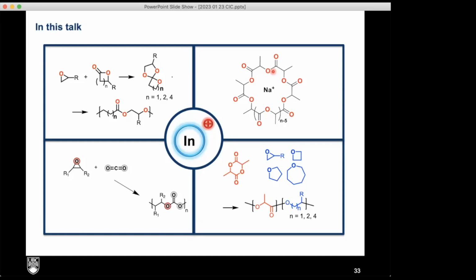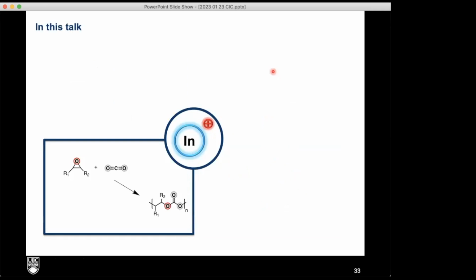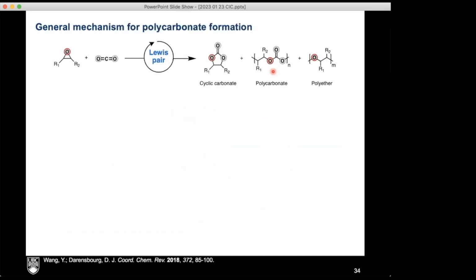And so the final part of this story is looking at the copolymerization of two more stories. The next one is the copolymerization of epoxide and CO2 to give polycarbonates. So this one is actually not a cationic indium, but I'll show you why that becomes relevant. So generally, when you take an epoxide and a CO2, there are three possible reactions that can happen in the system, and very often all three happen: you can form a cyclic carbonate, polycarbonate, or polyether. And the trick here is to be able to control either forming cyclic carbonate or forming polycarbonate.